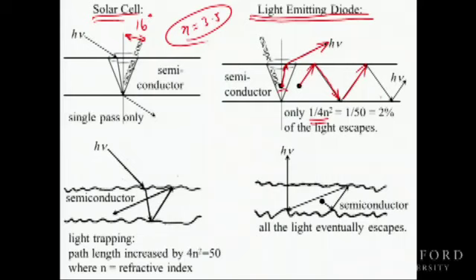So there's a solution for solar cells. I said you make the surface rough, and then the internal path length becomes much longer because it bounces around so much. It's actually 50 times. This 4n squared factor is 50, because index 3.5 squared is about 12, times 4 is about 48. It's actually 50. So that's a tremendous increase in path length.